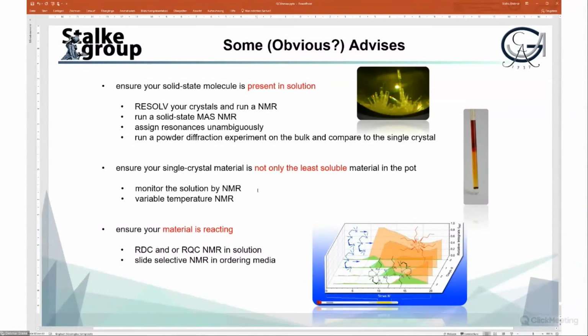So monitor your solution in the NMR and vary the temperature in the NMR. That helps a lot. Ensure that your material is reacting, which is, of course, redundant to say. However, sometimes it reacts with joint grease, or it reacts with whatever is in the pot with a solvent and not with your reactant. And this can be figured out by residual dipolar coupling or residual quadrupolar coupling NMR in solution, where you can take advantage of diffusion.